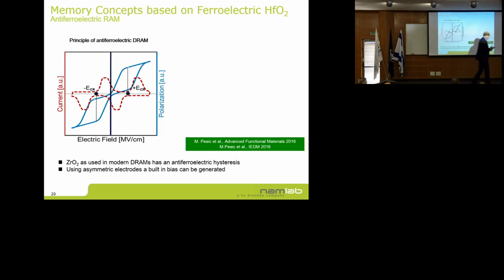But having this in mind, having the cycling in mind and limited by breakdown, we are looking into ways how to increase the endurance. And if we look at this anti-ferroelectric behavior that we can get for some doping concentrations, then it turns out that this can cycle much longer. Unfortunately, it's not a non-volatile memory because it has no remnant polarization. So the idea is, let's try to shift the x-axis here to use only one of these halves, and then we have a non-volatile memory again.